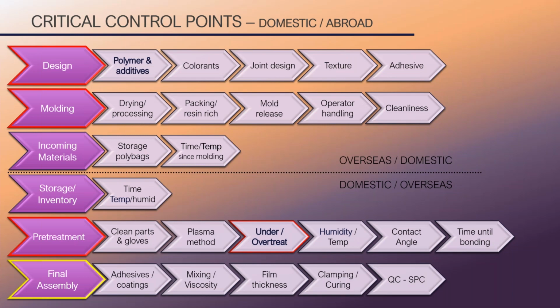Now, let's assume all of this is done correctly. We move on to final assembly. Adhesives and coatings: what type of adhesive has been used, or the coating? We have to have the proper mixing and viscosity. The dry film thickness needs to be 100% accurate. If it's too thick, then it's not going to dry or cure correctly. If it's too thin, process inconsistency.